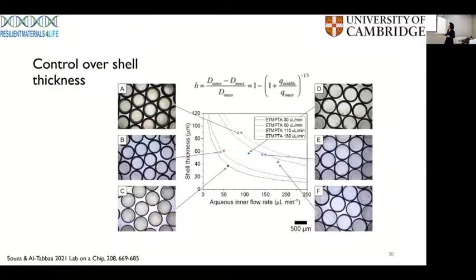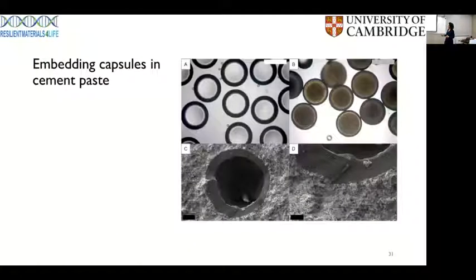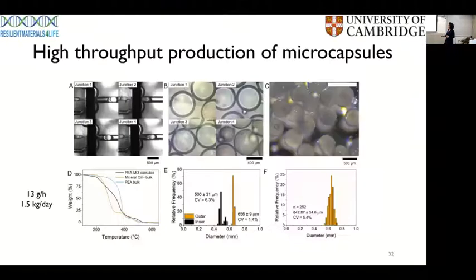We can control the shell thickness of these microcapsules with this equation. So when you increase the inner flow rate, you decrease the shell thickness of these capsules. So you can work from thick, which is not interesting for us, all the way to thinner shells. Playing with different acrylates that are going to offer a better bond with the cementitious matrix as well. So this is an SEM of these capsules in cement paste. And here is the beloved CV that Dave was talking about.